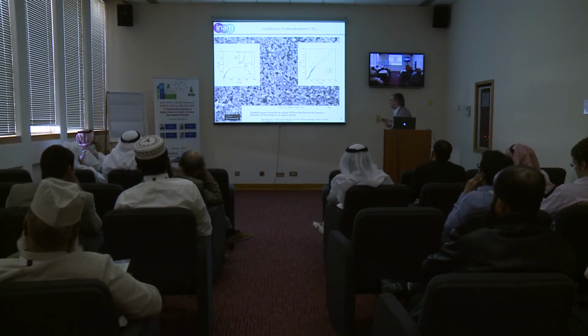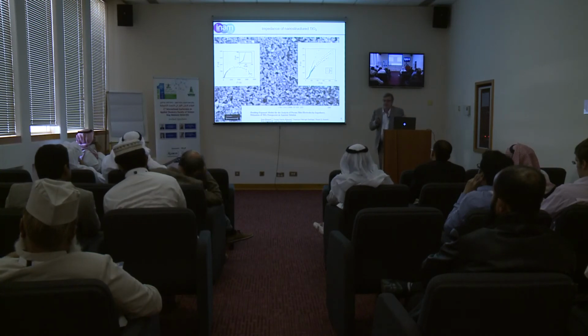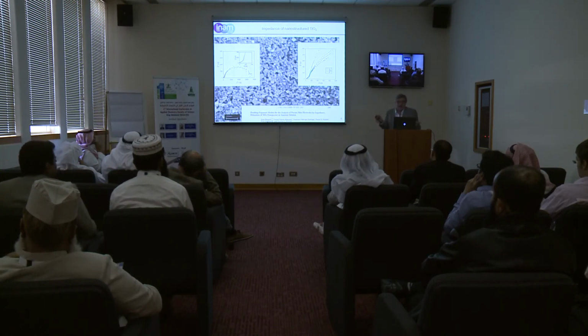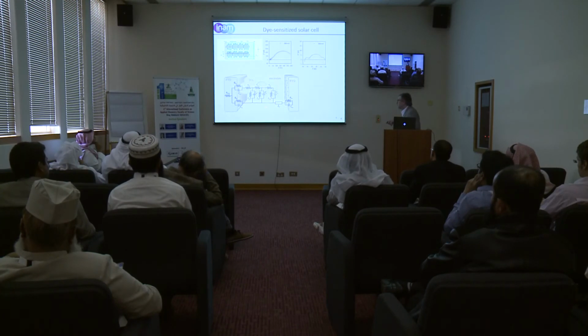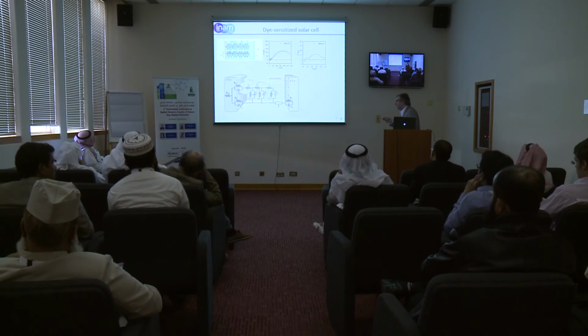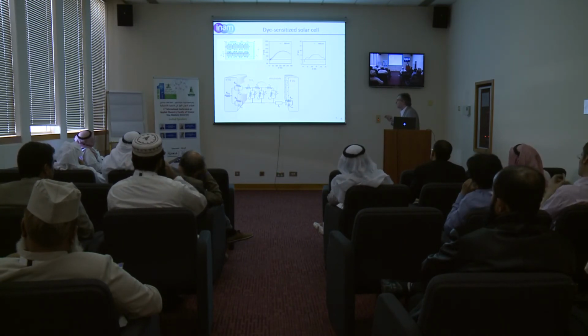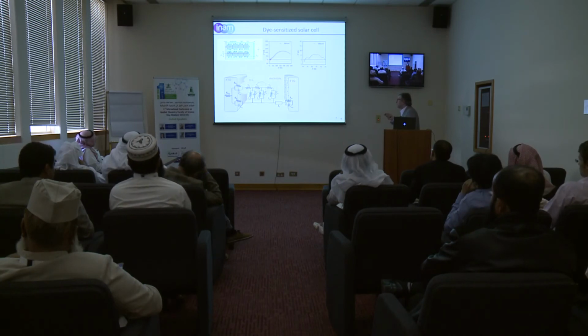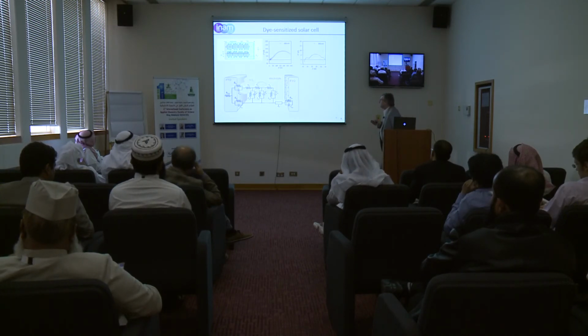When you understand them, good; sometimes you don't understand them, and the information is there, but you cannot see it. But this problem we could understand, and the way to understand it is to formulate this type of transmission line circuit, in which we have resistance for electron transport, and then here we have the charge transfer and charge accumulation element. So all this gives rise to these spectra. This we understand very well, and it has been applied by now by hundreds of people, and people learn it.